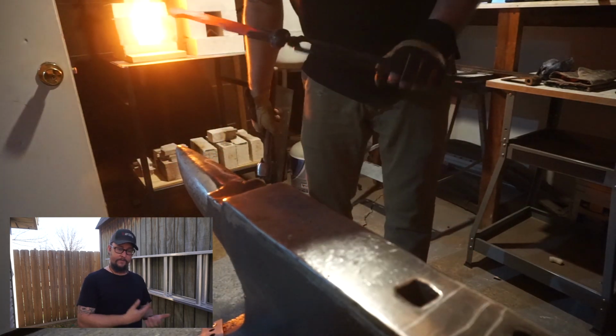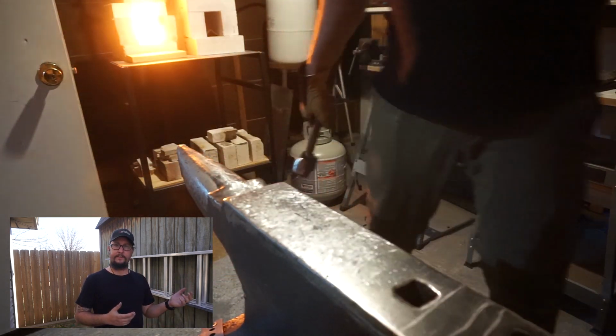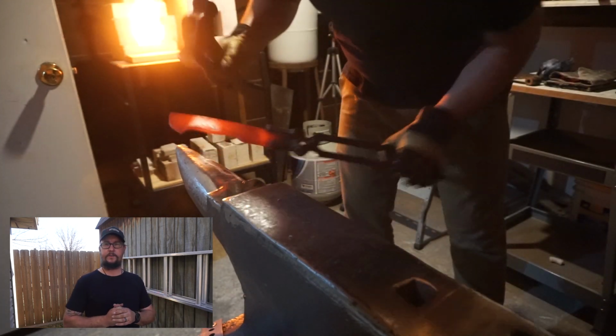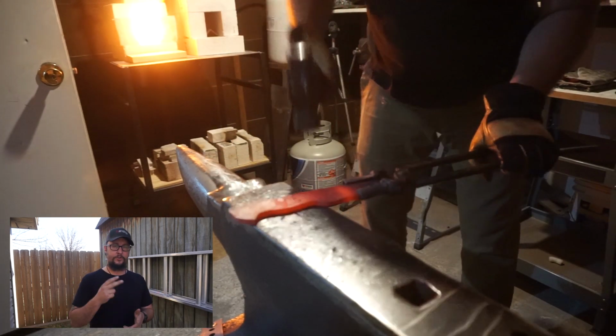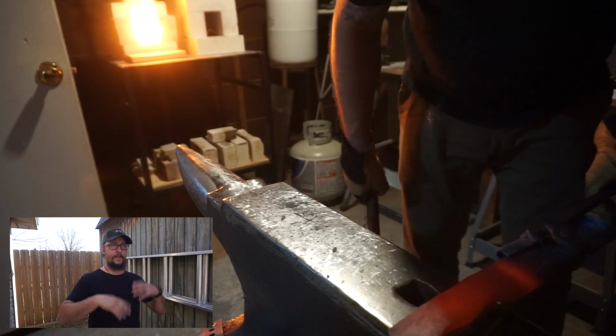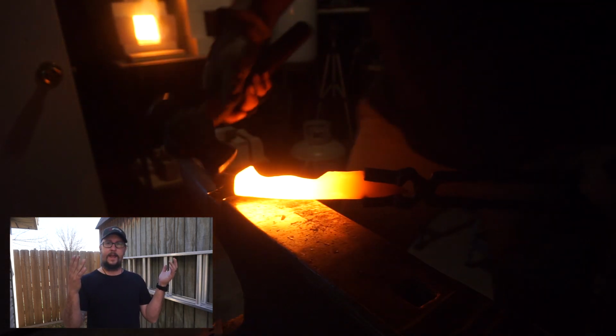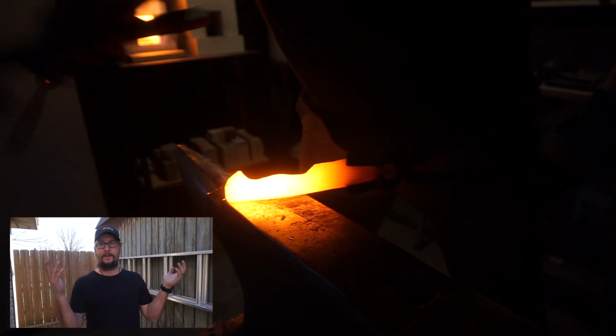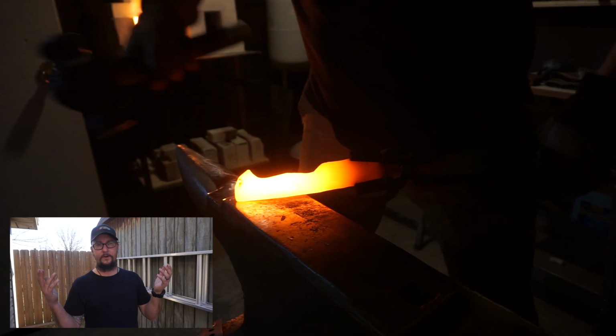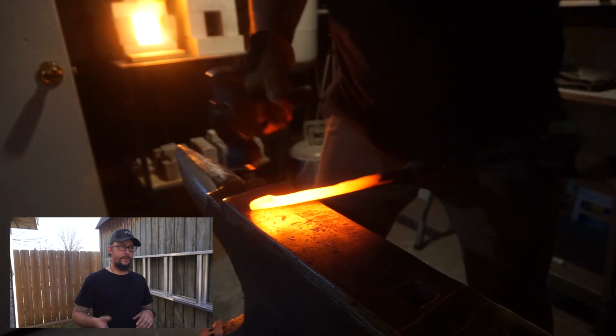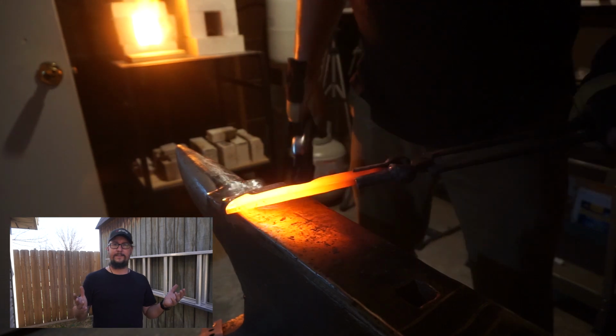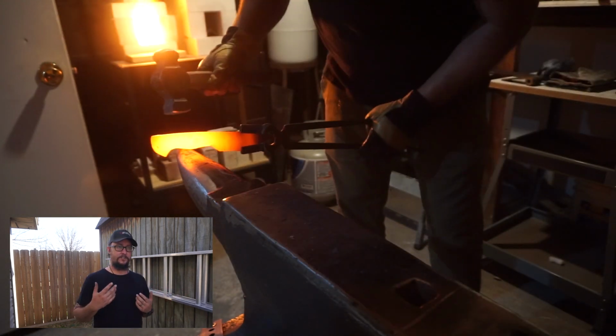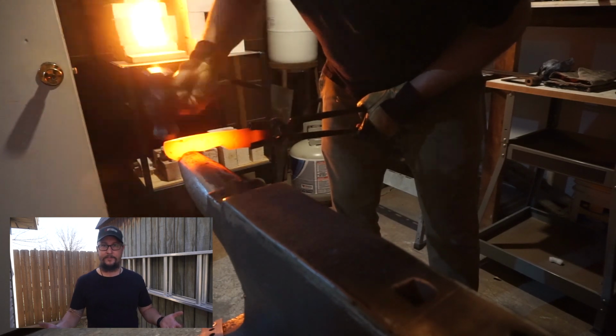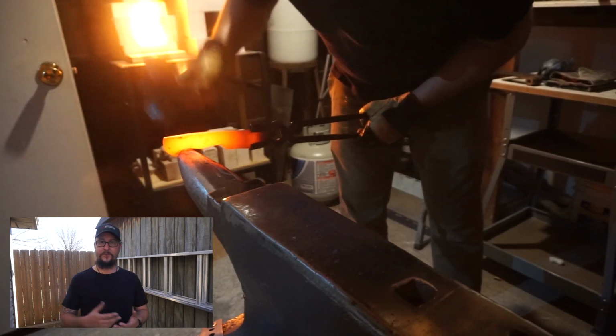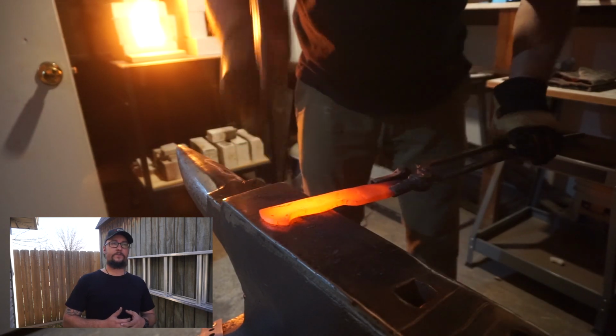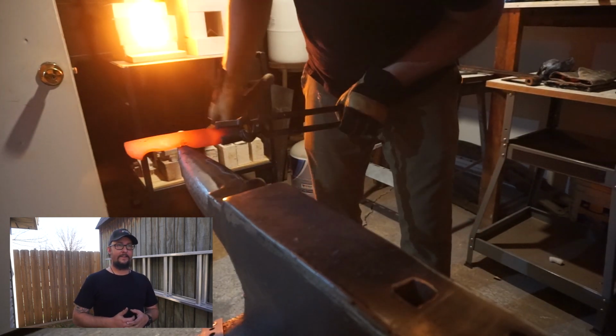Me personally, whenever I first started doing knives, with my oven, I was doing 375 degrees for about 2 hours, and I was doing two 1-hour cycles. So I was bringing it up to 375 for an hour, and then letting it cool, then bringing it back up to 375 for an hour and letting it cool. And then I started doing a little more research and realized that there's no point in doing the 2 different cycles, because you can just do it for 2 hours. It's the same process. You can do it for 2 hours. Or you can do something like what I do.